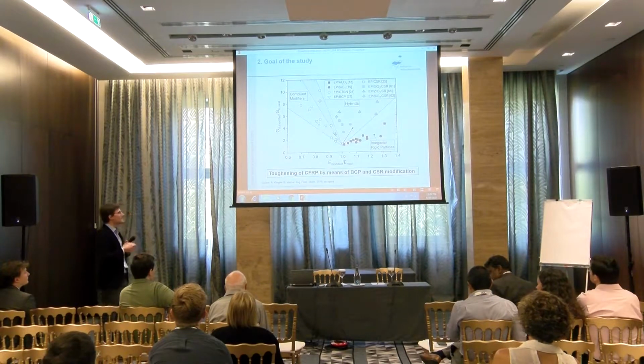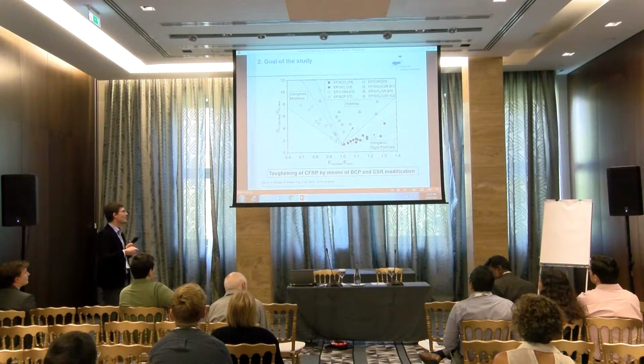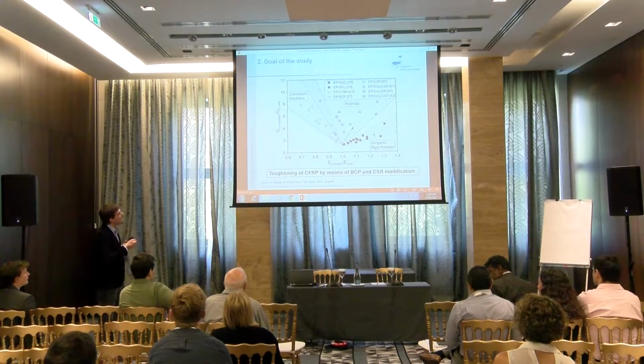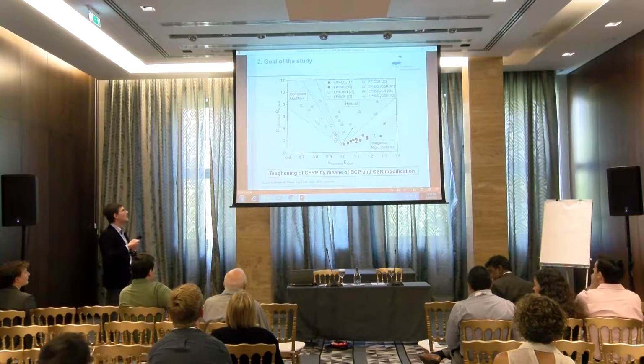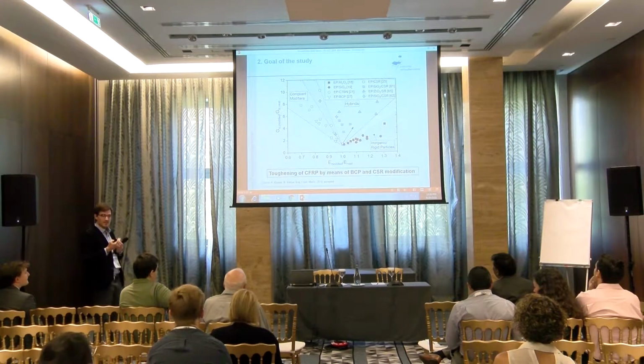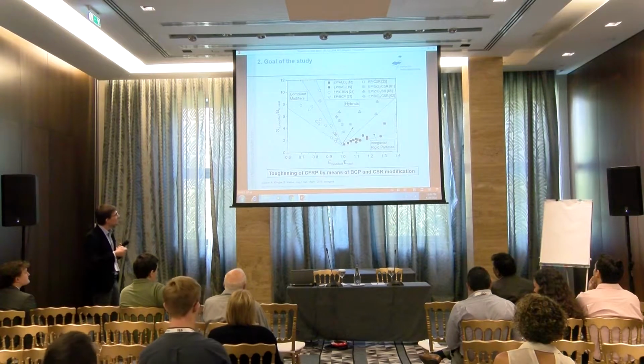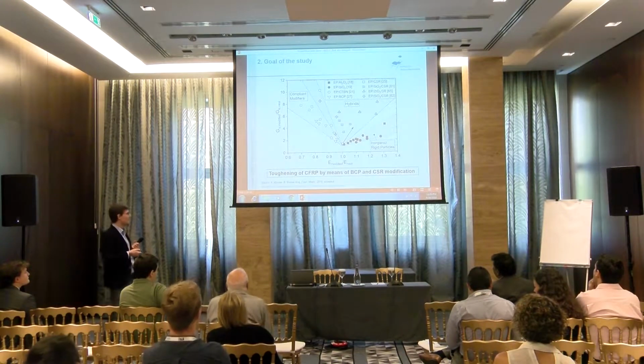The goal of the study is if you take a look at this graph, on the x-axis there's the normalized stiffness, and on the y-axis you can see the normalized energy release rate. First, a look at the compliant modifiers taken from different literature resources. You see that we are usually decreasing the stiffness. It's a drawback, right? But we can strongly increase our energy release rate, our fracture toughness. On the other hand, inorganic rigid particles lead to a strong increase in stiffness. However, the toughening efficiency is limited.